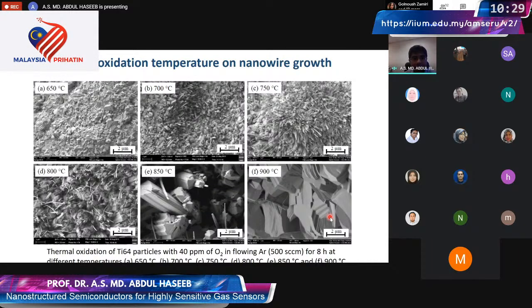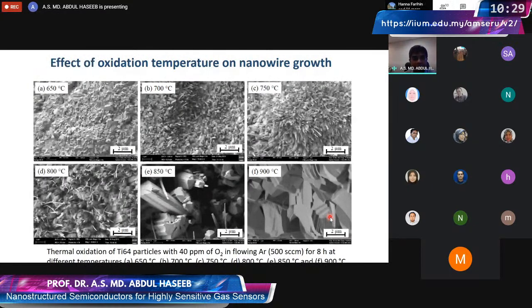This is the effect of temperature. We grew the nanowire in a controlled environment where we have argon gas mixed with tiny amount of oxygen, because we cannot do the oxidation in air. If you do that, then you create thick layers of oxide. We don't get the nanowires. Now, by looking at these pictures, you see that from 650 to 900, at high temperature, we don't get nanowires. These thick bundles of oxides form here. And we get nanowires in a narrow range.